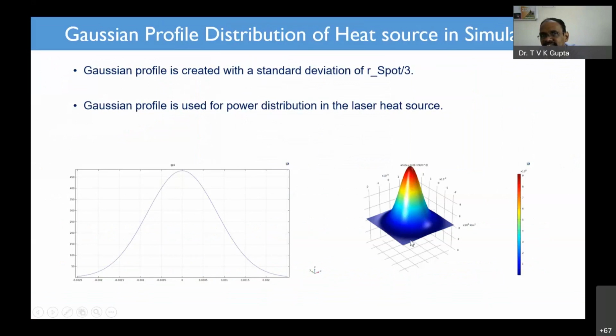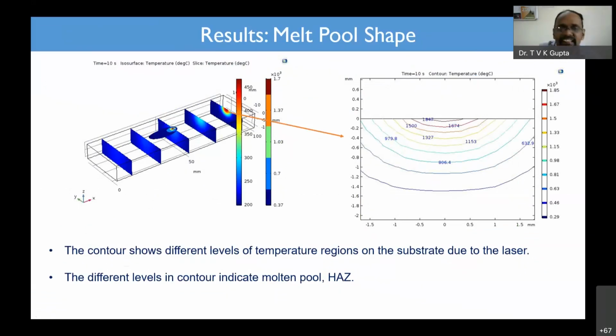The power profile is the Gaussian distribution, and you are going to see the temperature profile along the thickness, along the width, and also along the thickness. Now, if you see at each and every layer, each and every point, you can always see there is a temperature phenomenon happening. The temperature is being transferred to the substrate also. Even at this location, the temperature is somewhere around 600, 700 degrees centigrade in the substrate. On the melt pool, you are going to get 1900 degrees centigrade. So we tried to simulate this and also check whether we are getting the same with these parameters or not.